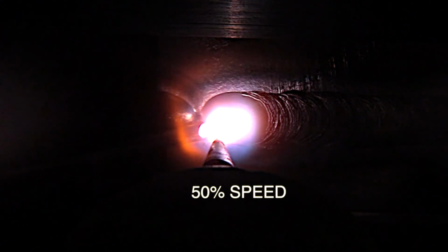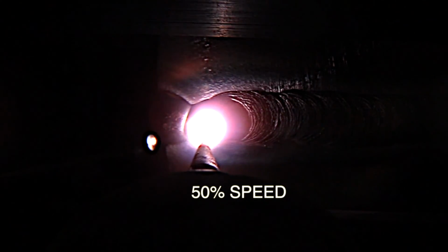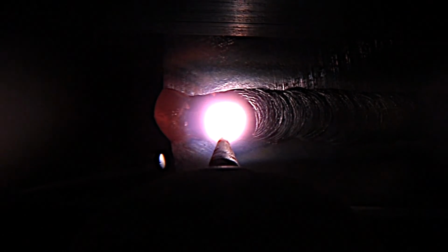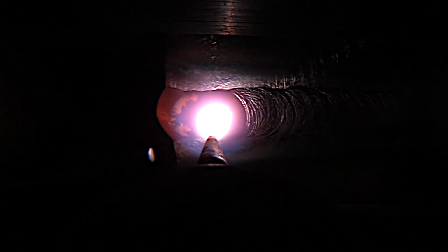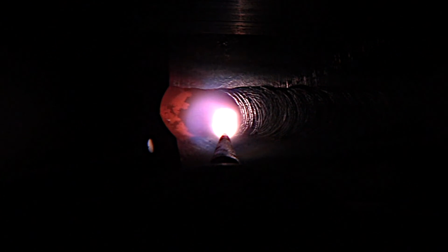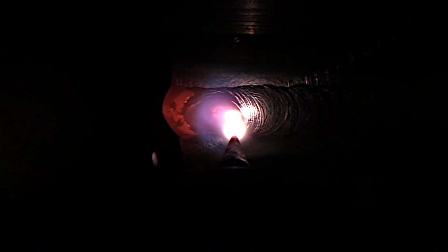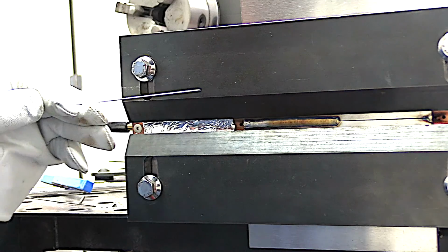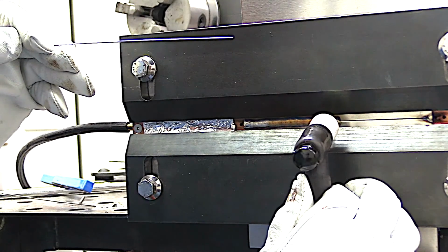So I'm going to show this in slow motion here. This is half speed. I'm coming up on that end tack. I'm really eyeballing the left side of that puddle and slowing down, tapering off, letting it soak for a second, and then tapering off the amperage. And I know I'm going to get 100% penetration all the way end to end, and I'm not going to blow the end away by doing that.